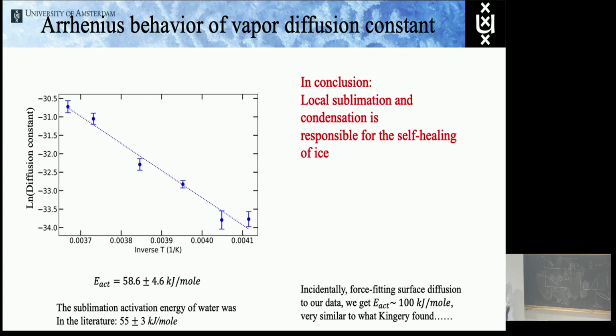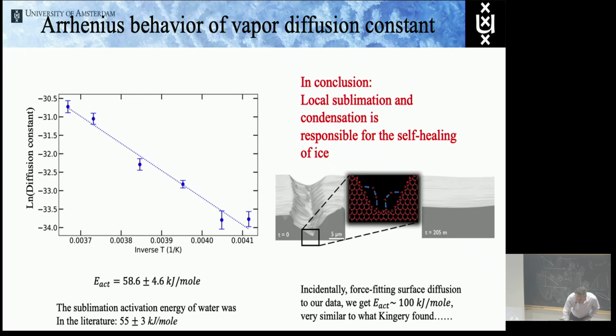If we go back to the strange activation energy that Kingery found, we can actually force fit the surface diffusion model onto our data, and then we get another activation energy, and we actually get almost the exact same value that Kingery got, which was not surface diffusion. So we think that if Kingery had gone to lower temperatures, as we did, and did more measurements, he would actually have agreed with us. And so the conclusion is local sublimation and condensation.